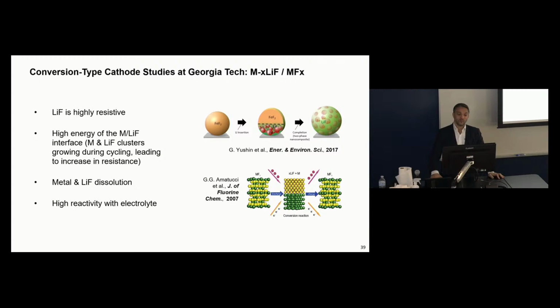In addition, one of the biggest challenges we found was that the interface between lithium fluoride and metal is high energy. So lithium fluoride doesn't like to be near the metal, or the metal doesn't like to be surrounded by lithium fluoride. And so they tend to overall ripen or increase in dimensions over time, and you have even larger mass transport limitation. Furthermore, both metals and lithium fluoride can dissolve into electrolyte at high voltages. And furthermore, these metal nanoparticles that you produce often serve as good catalysts. And so they decompose the electrolyte and have all sorts of side reactions that, again, are important to avoid.